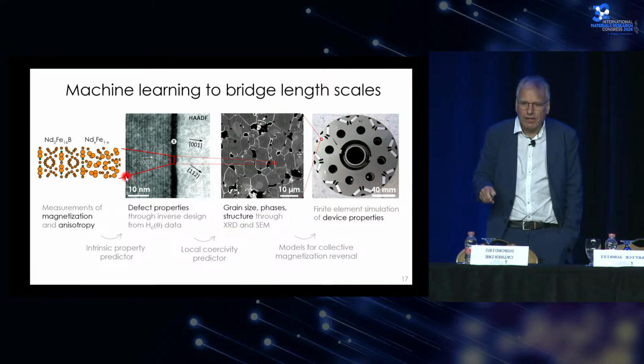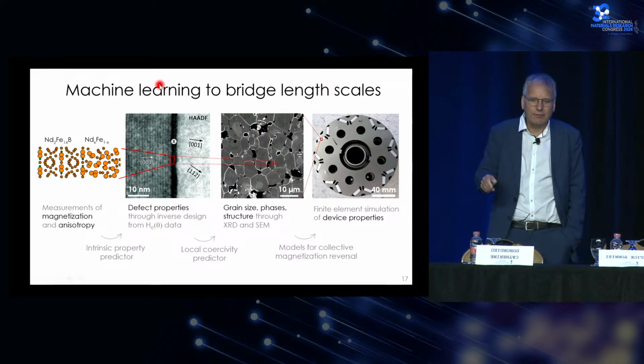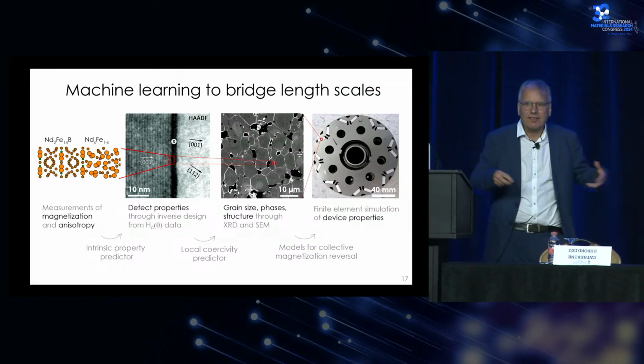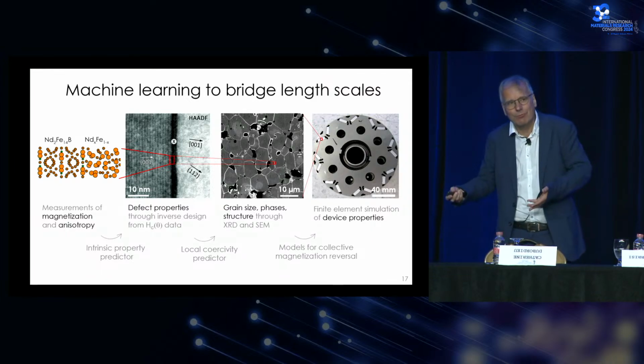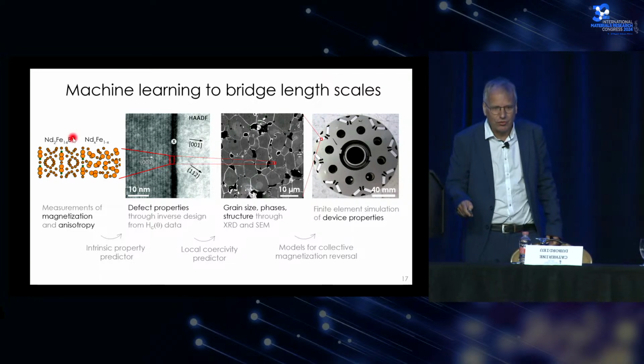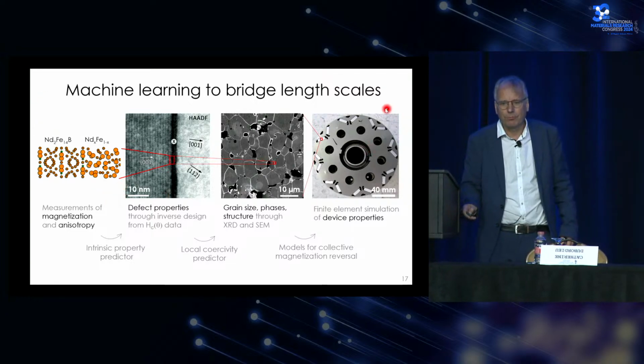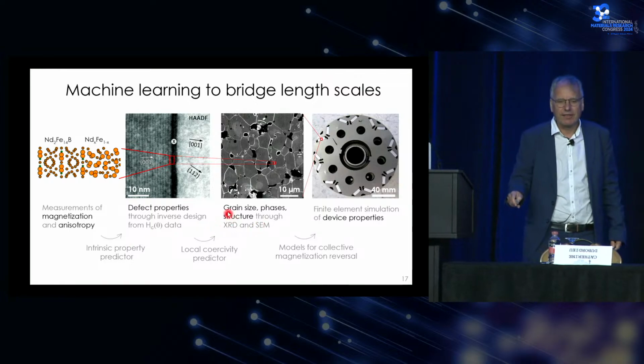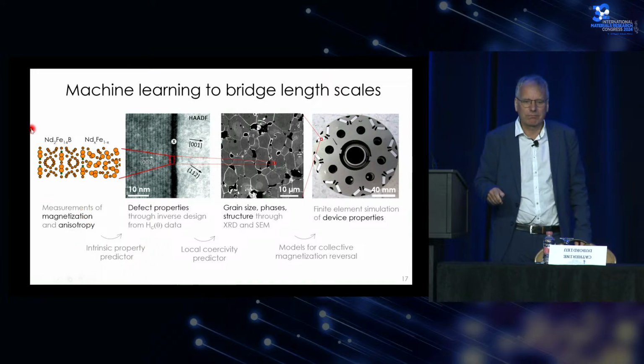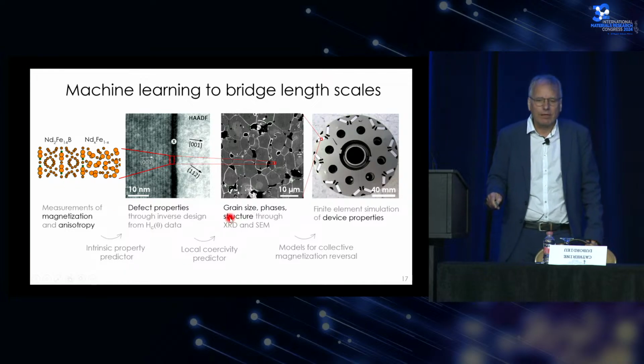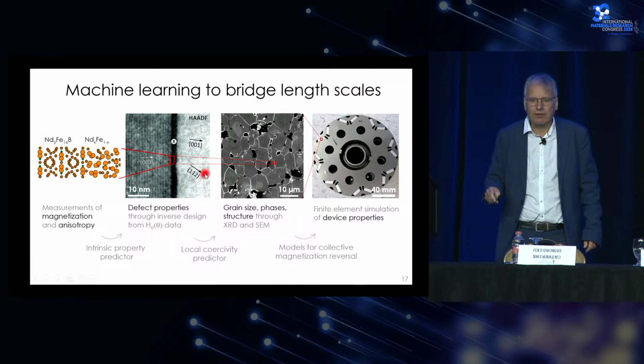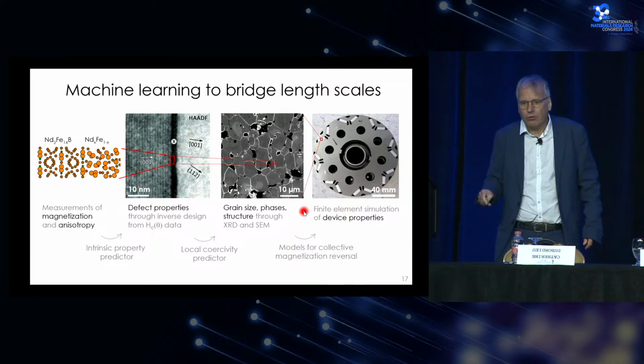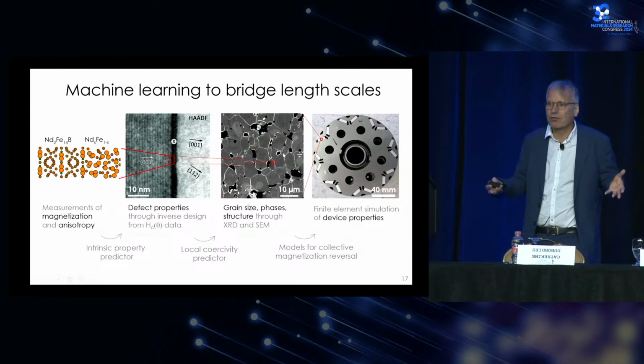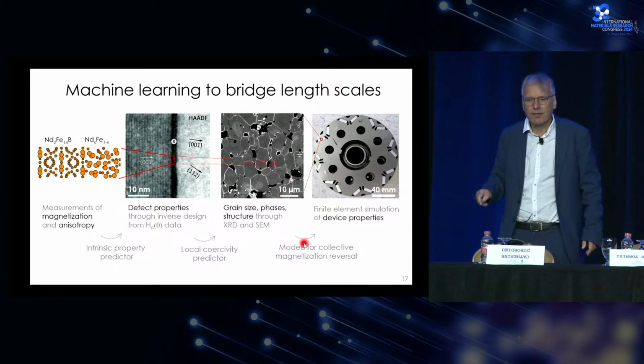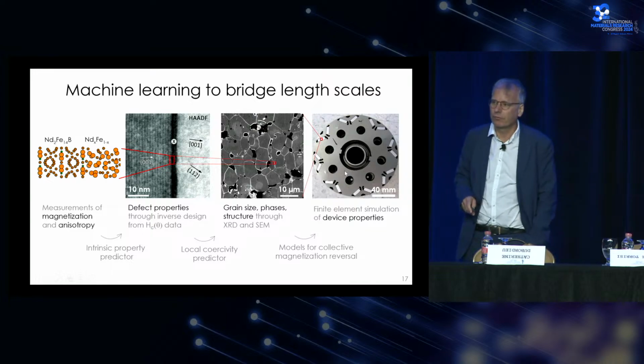But now, if we want to optimize the material at a certain length scale, we also need the information from the smaller length scale. But this is not readily available because we need to do ab initio simulations or measurement. And so in order to make this information from the lower scale readily available for optimization on the larger scale, we need to do machine learning surrogate models that, for example, give us the intrinsic magnetic properties when I give the chemical composition as input, that will give us the local coercive field if I give the granular structure as an input, or which tells me how all these grains will reverse if I give the grain structure as an input. So we use machine learning models in order to bridge the different length scales involved in a magnetic device.